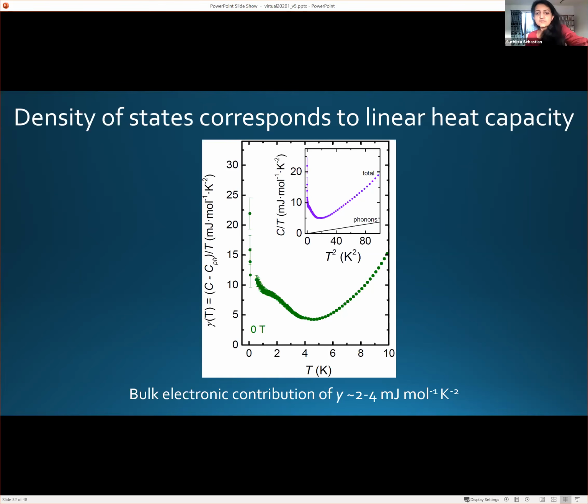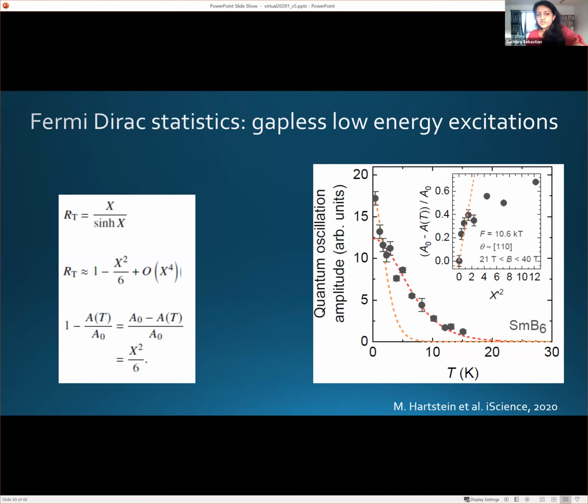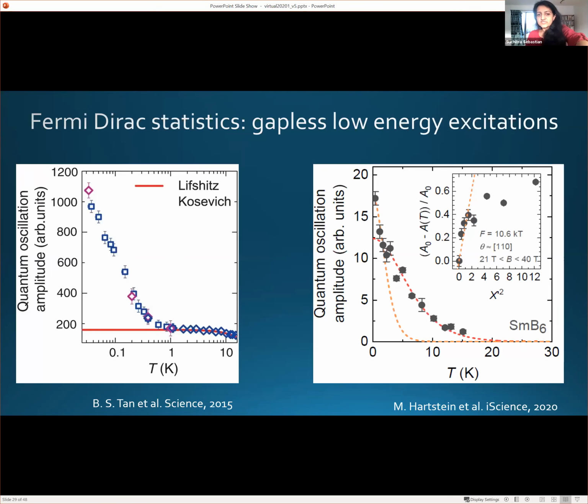Oh, you mean down? It's below about 500 millikelvin. Do you have oscillations across that temperature? Yes, we do. The oscillation amplitude is what changes, right? Below 1 Kelvin, on my screen now, on the left, we went down to dilution fridge temperatures, and this is on a log scale, so it's artificially zooming that. But yes, the oscillation amplitude does dramatically increase at low temperatures.